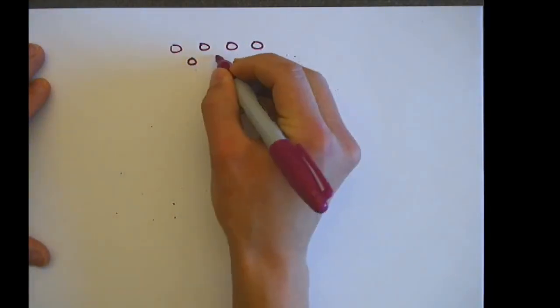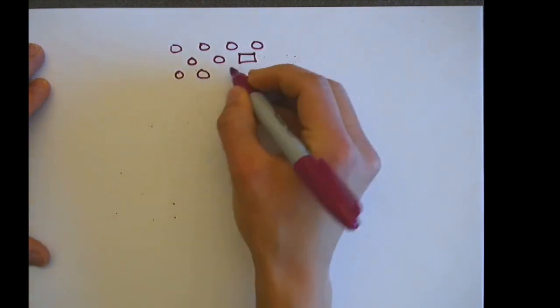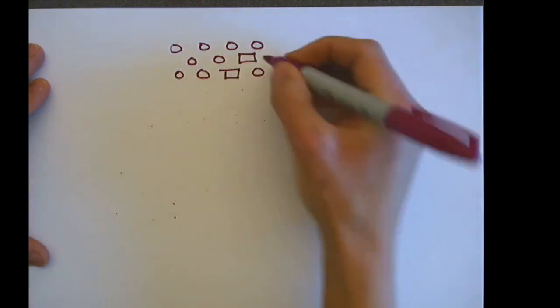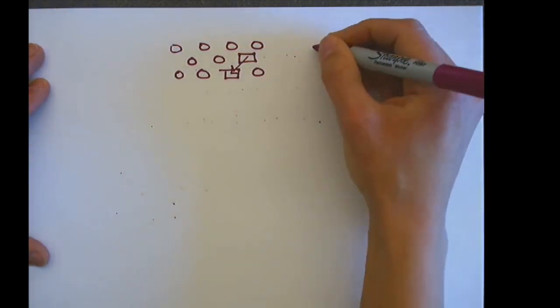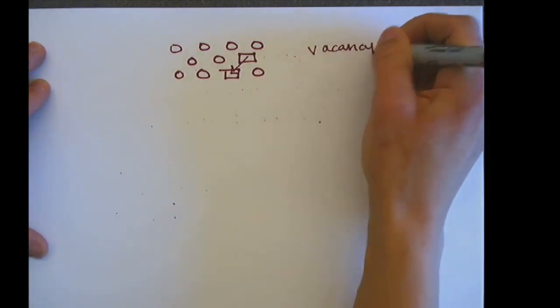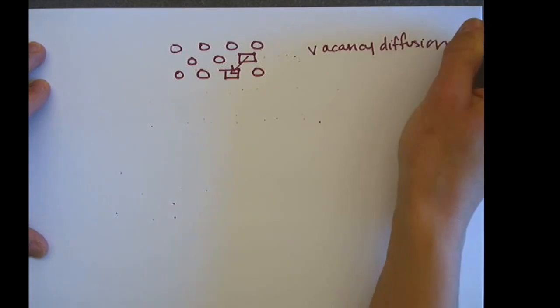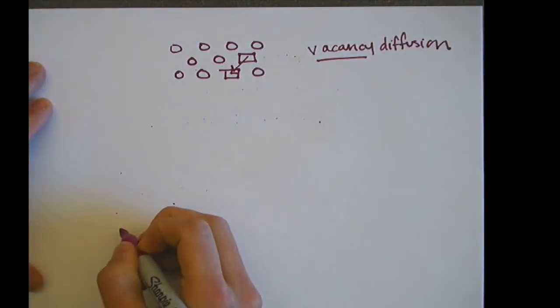Next, we're going to show some diagrams of diffusion, some mechanisms of diffusion. First, I'm going to diagram vacancy diffusion. Now these boxes here that I'm drawing, those are vacancies, and we're going to see the impurity atom moving from vacancy to vacancy, vacancy diffusion. So when an impurity atom moves from vacancy to vacancy, it strains the lattice. And so this one, it induces a lot of lattice strains because the molecules are large and they're moving from each vacant site.